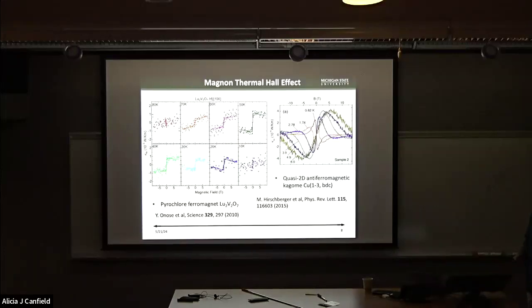The magnon thermal Hall effect has also been observed in several systems, only a few systems. Here I listed a couple of examples. One example is the lutetium vanadium 227 system, which is a pyrochlore compound. Another example is Cu(1,3-bdc), which is the 2D Kagome system that was described in the previous slide. If we take a close look at the y-axis scale of the thermal Hall conductivity, we can see that the thermal Hall signal of both compounds is very small, in the range of 10 to the minus 3 or 10 to the minus 4 watt per meter Kelvin.